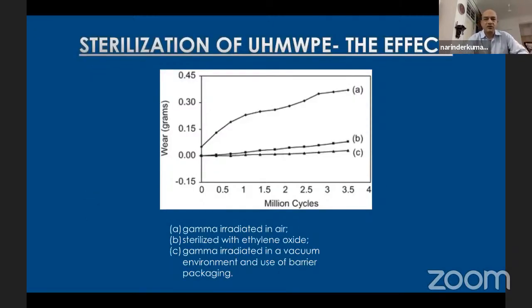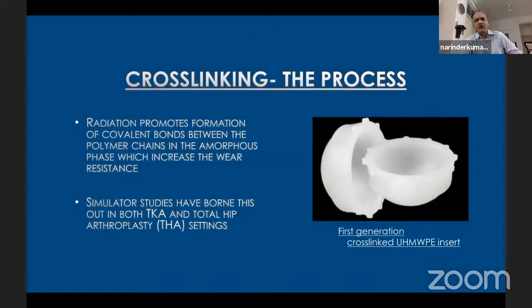Once you test these things for wear, the gamma irradiated poly in a vacuum environment with use of barrier packaging has the least wear rates, and gamma irradiated poly in air has the maximum wear rates. I won't bother you with the technical details of cross-linking, except that it's various doses of radiation which cause the cross-linking, and simulator studies have shown they definitely increased wear resistance and decreased wear particles.